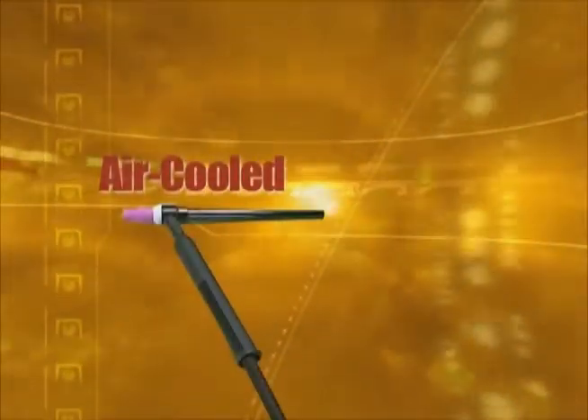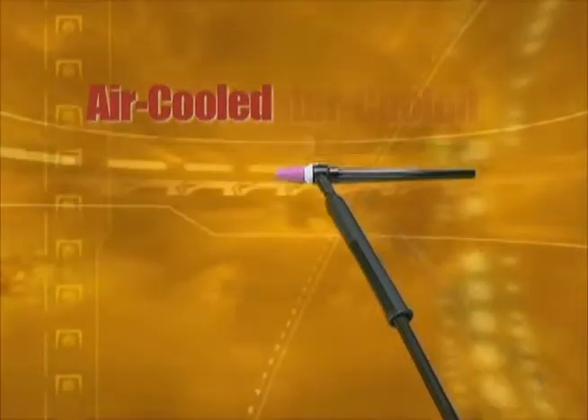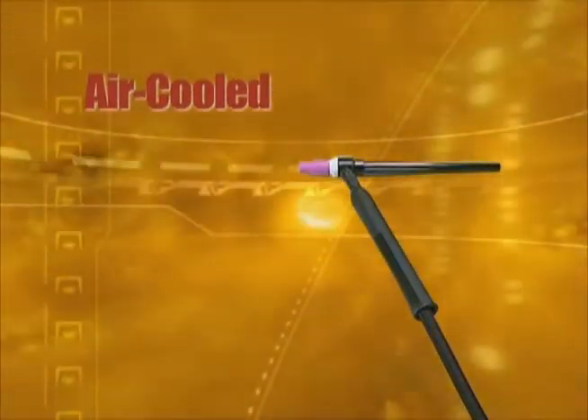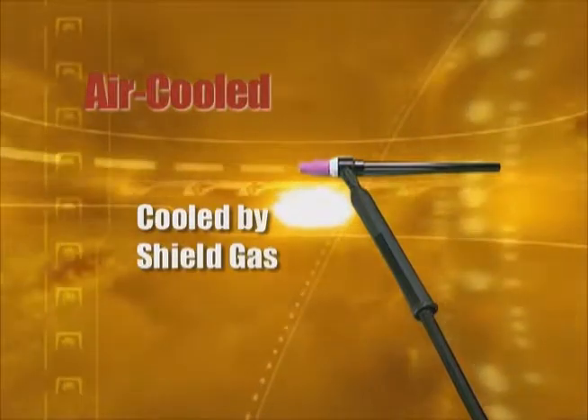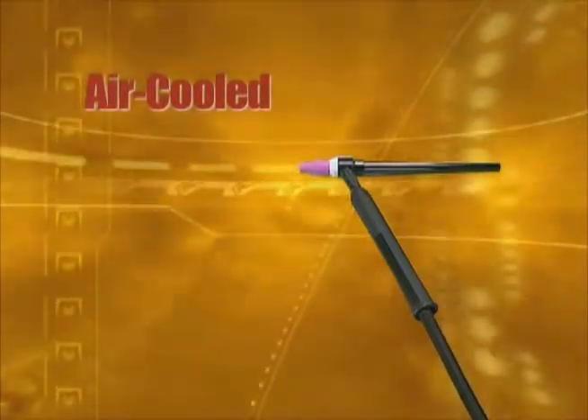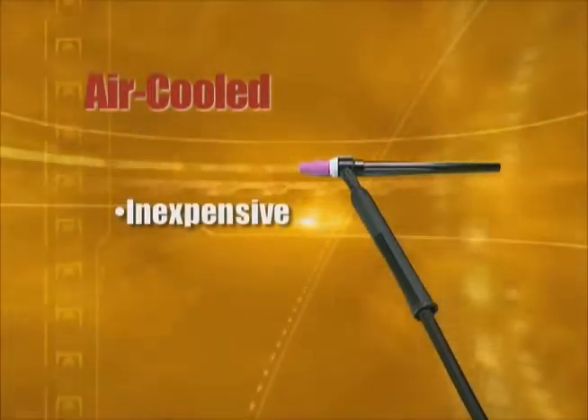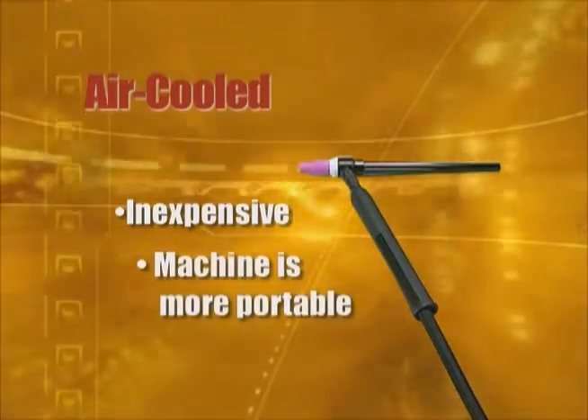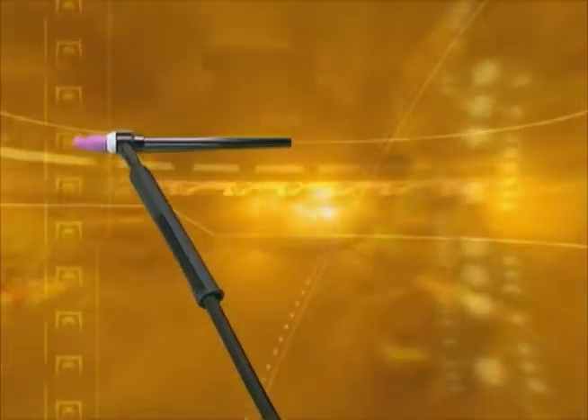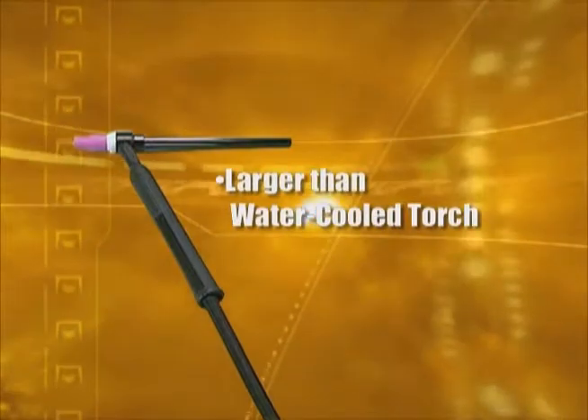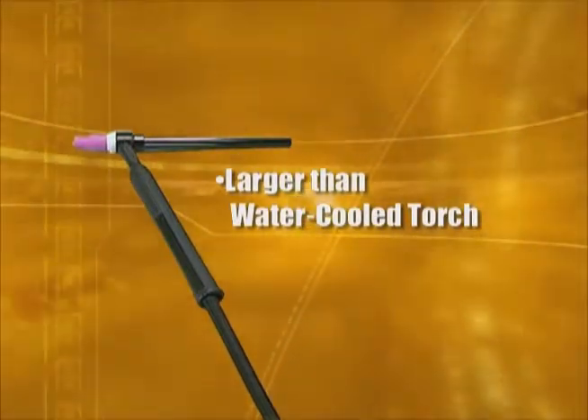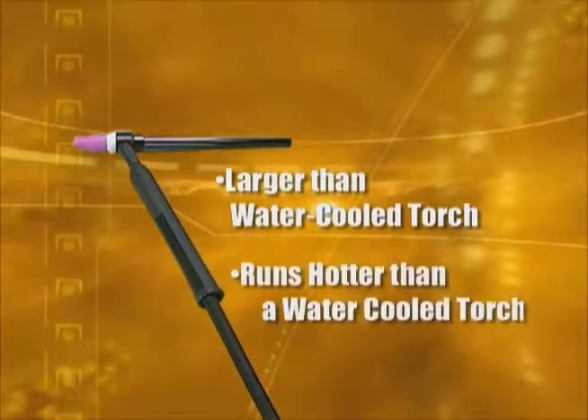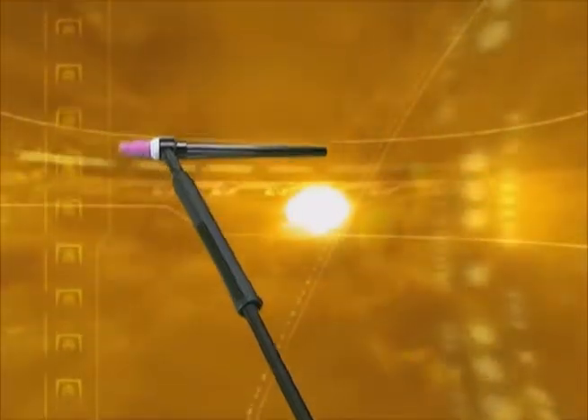There are two main types of TIG torches, air-cooled and water-cooled. An air-cooled torch is not really cooled by air, but is cooled by the shield gas. The benefits of an air-cooled torch are they tend to be relatively inexpensive and make the machine more portable than a water-cooled torch. The drawback is they tend to be larger than a water-cooled torch for the same amperage, and they do tend to run hotter than a water-cooled torch.